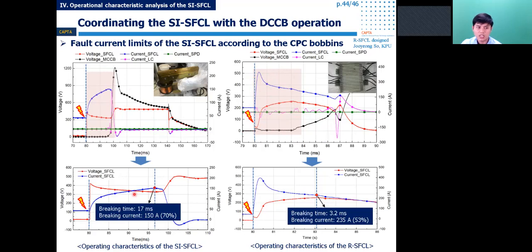In case of using the SFCL, because it has a large inductance, the large inductance can reduce the current rising rate, di/dt. So there was no surge current like a resistive SFCL, because it reduces the di/dt, so the circuit breaker can detect and break the fault current more slowly. You can see especially the saturated SFCL can greatly reduce the breaking current level, much more than the resistive SFCL. So here it can limit the fault current up to 70%, and in case of the resistive, only 53%.